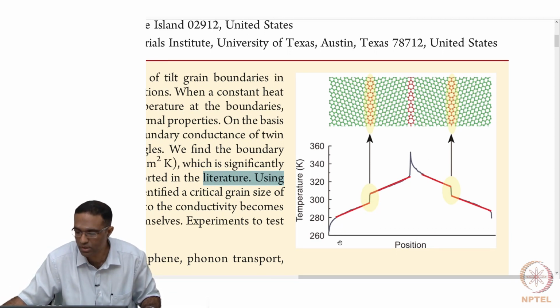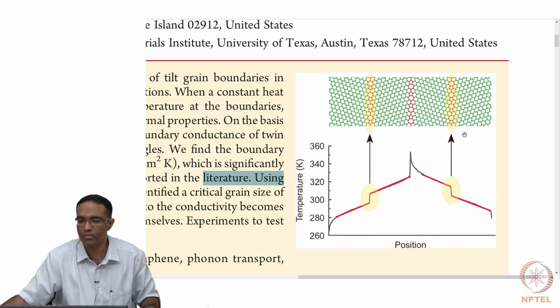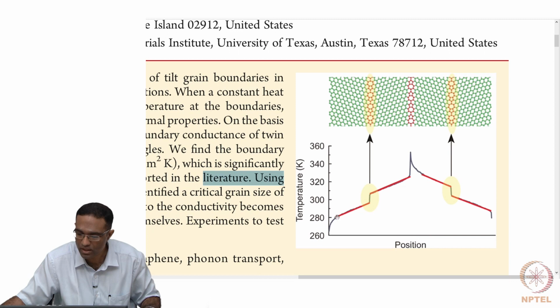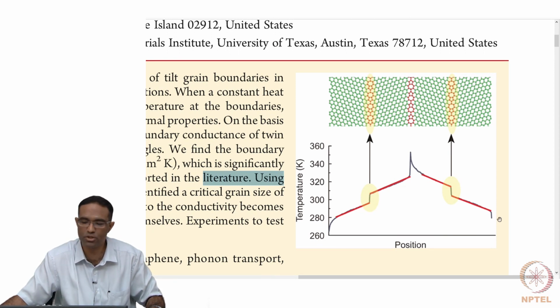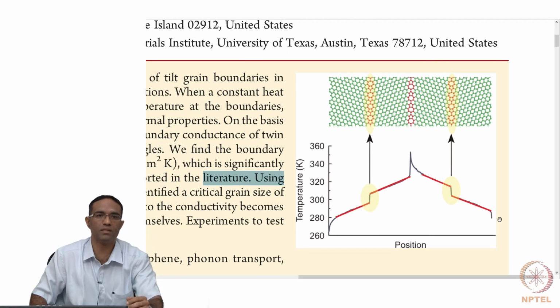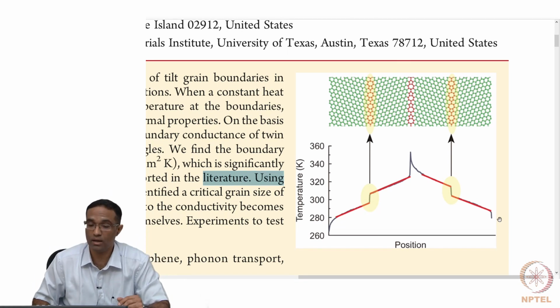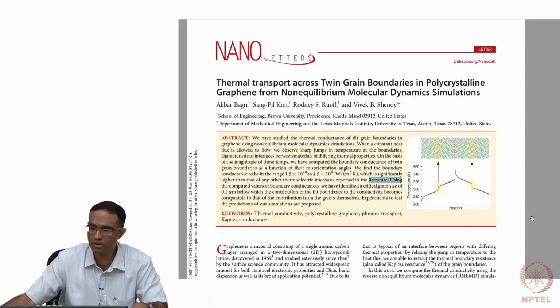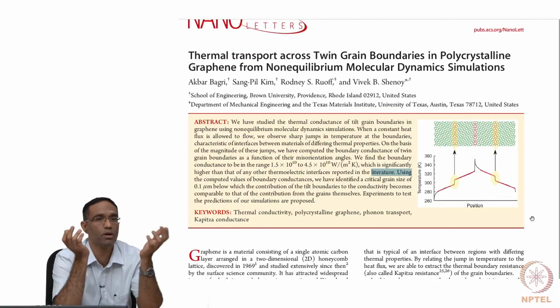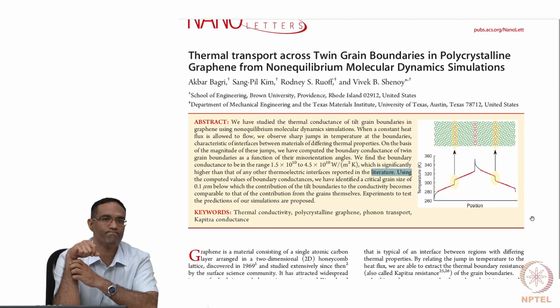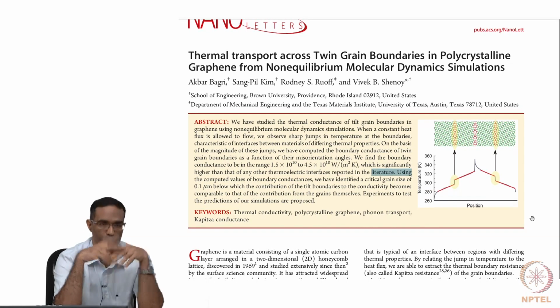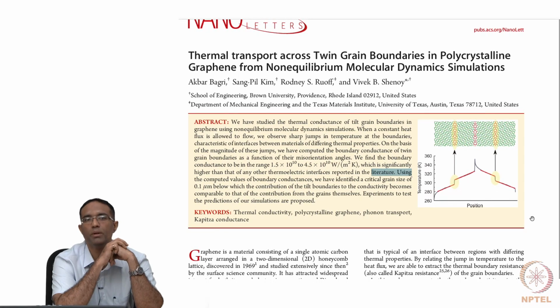This is the plot of the temperature versus position across this distance, and they see that there is a linear variation in temperature with position here. You can take the slope of this to relate that to your thermal conductivity. But at this particular point where the grain boundary exists, there is a sharp jump, indicating that there is a higher resistance to heat flow at these grain boundaries. This has also been done not only on graphene sheets but also on other bulk materials with grain boundaries, so it's possible for us to find out thermal conductivity as well.